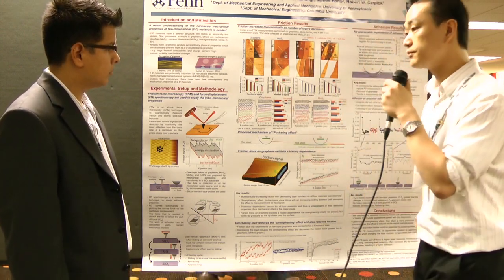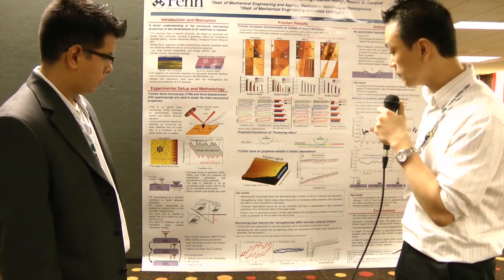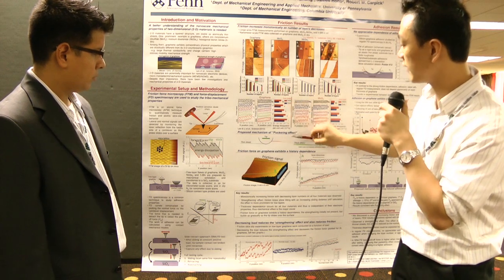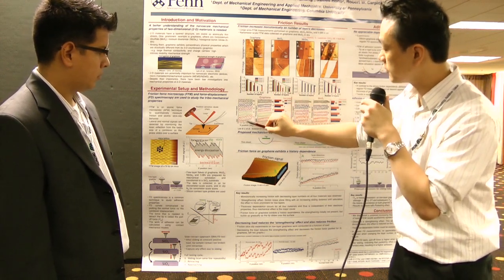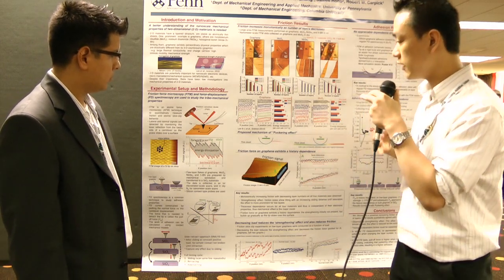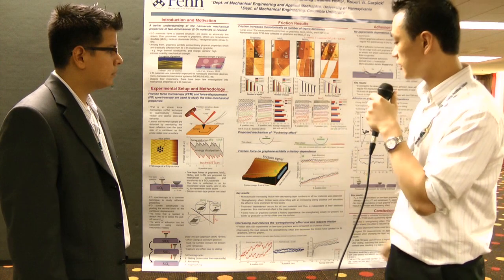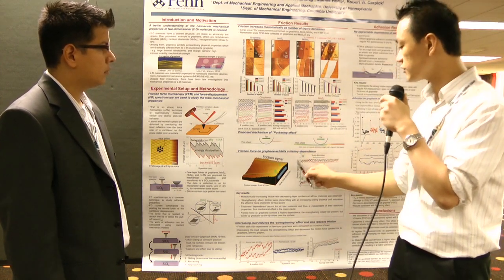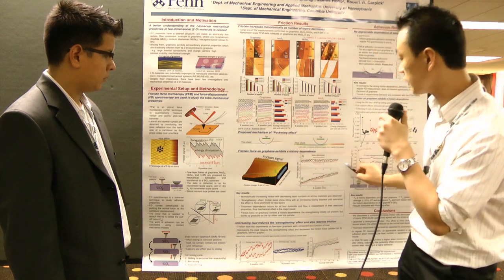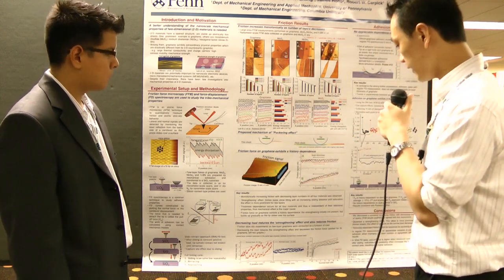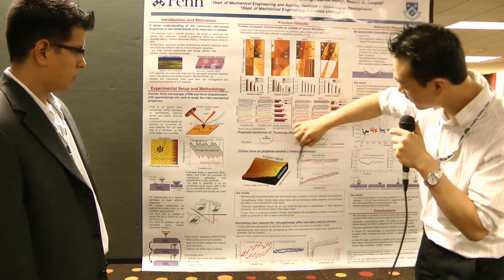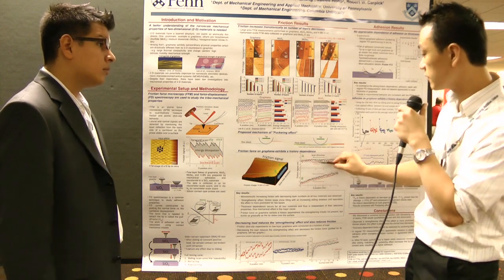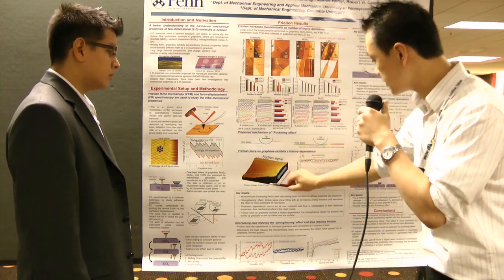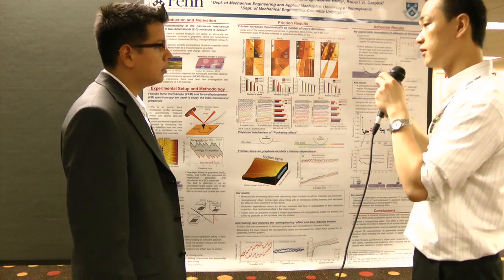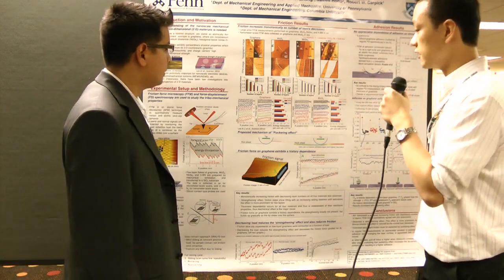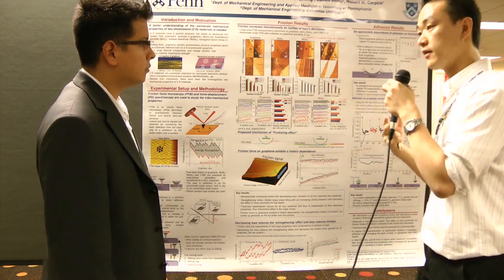Also, we saw the so-called strengthening effect, which is related to the static friction, building up as long as the sliding proceeds, and that's also for all these materials. We see a sliding history dependence, which we call the strengthening effect. Here you see at the beginning of the scan, the friction is not tilted much, but as the scanning proceeds, it's getting tilted. The other thing is that the friction is dependent on the layer thickness. That's very striking, and we didn't expect it.